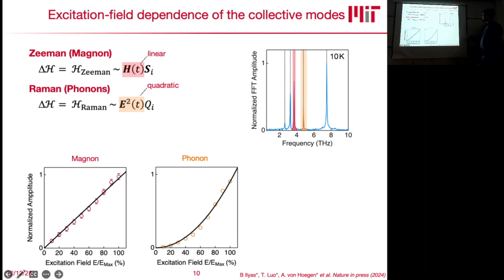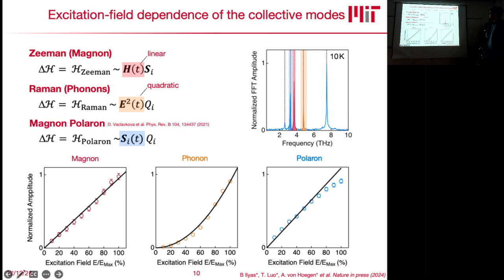Then we picked this mode here, which people have already seen before in these Raman measurements. It's just a phonon. It doesn't hybridize with the magnon, and therefore people just call it a Raman phonon. And a Raman excitation scales with the square of our electric field, which therefore should also show an excitation field dependence that goes with the square of our excitation field, which is exactly also what we find for this phonon. However, then there's this other mode, what people call this magnon polaron. And so this is now this hybrid particle, which is half magnon, half phonon. So how does that scale?